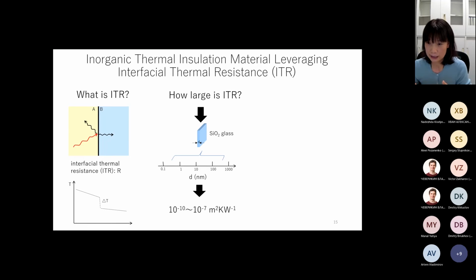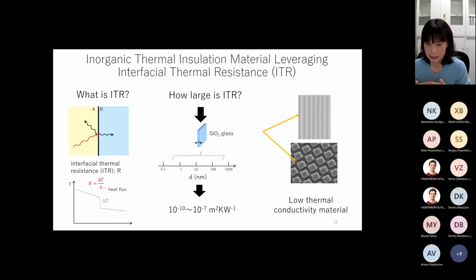Then, how large is the ITR, interfacial thermal resistance? We can compare it with the thermal resistance of SiO2 glass with thickness of D. Then the ITR of a solid surface can be equivalent to a D ranging from several nanometers to several hundred nanometers. So this gives us a hint that if we can design an interface with very high ITR, and we make nanomaterials including many such interfaces, we have a chance to develop a material with very low thermal conductivity. So this is our concept. But the point here is we have to design an interface with high thermal resistance.